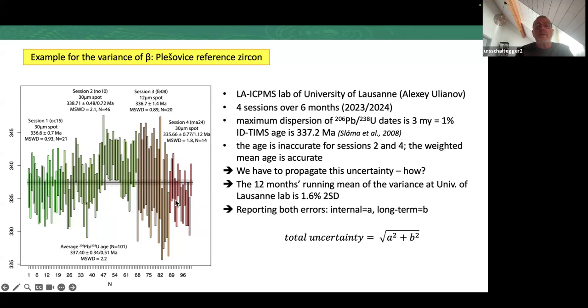This one is too old, this one is too young. So that means we have to propagate these uncertainties to our unknowns, because these unknowns here are too young. This day I measured them, they will be too young, these will be too old. And what we do in Lausanne, we have a running mean, or Alexei has a running mean of 12 months, where he does statistics on 12 months Plešovice measurements from anybody who is using the lab, and he comes at something like 1.6% of two standard deviations.